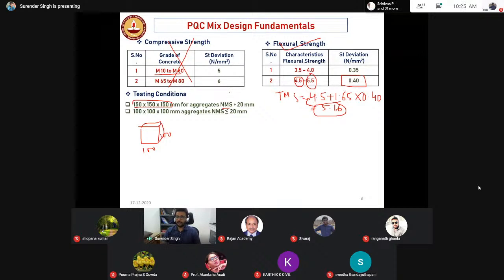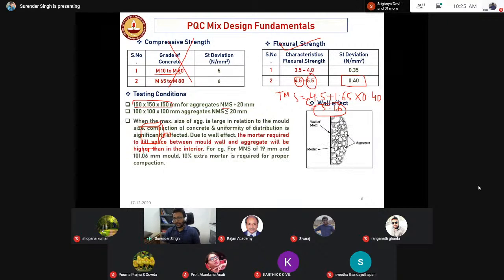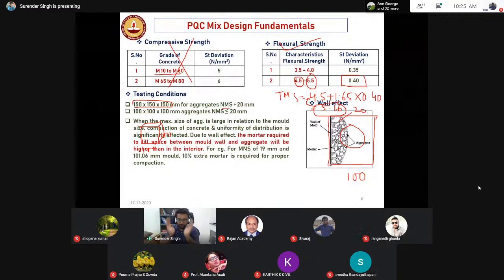But why is it happening? Because of the wall effect. Wall effect means, let's say we did one test here. You are making a cube of 100 mm, and you are taking the aggregate nominal size of, let's say, 20 mm. So what will happen when you compact this specimen? The aggregates will be compacted easily in the interior. But because there is a steel or iron wall, the walls of the mold, the aggregates could not be compacted at the walls, and this is known as the wall effect. When the aggregates are not able to be compacted, the voids will be higher, and if the voids are higher, obviously it will require more cement paste.